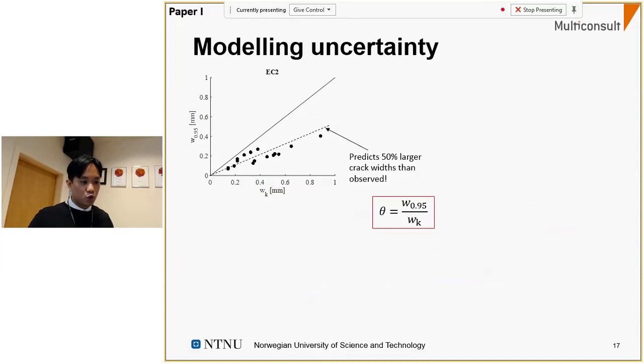The formulas we would then use to satisfy the crack width limits with these large covers would lead to much higher reinforcement amounts than what is actually necessary compared to what we would have seen in real experiments. That is because the formulas are formulated in a way that the mechanics are violated and inconsistent, and do not really account for the true behavior of reinforced concrete ties. That's why they have been empirically adjusted instead of actually improving the mechanics behind the formulas. But the new set of formulas we're working on should be able to predict crack widths that are more consistent regardless of the cover size and the bar diameter.